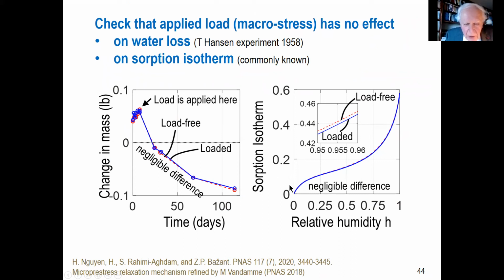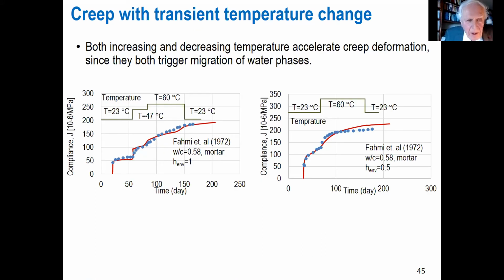Same thing for sorption. The isotherm, we know it's independent of whether there's compression or not. That's satisfied. You see negligible difference. Of course, if you expand it, we see some difference in calculations, but that's totally negligible. So that's an important check on all the models of moisture. By the way, this defeated the consolidation theory of concrete creep in 1958. It took time to sink in, but that was the end. At temperature changes, it's also modeled.